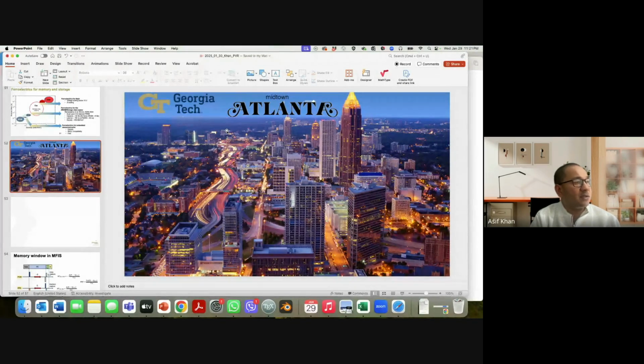And in general, we see that alumina gives the best enhancement of memory window in this kind of structure. We call it a laminated structure. And we think that it's because alumina has a property of inducing traps within its bulk as well as at the interface. So long story short, interface traps, we think, play a big role in how this device operates and how it allows us to exceed the fundamental limit of the ferroelectric memory window of ferroelectric field effect transistors.